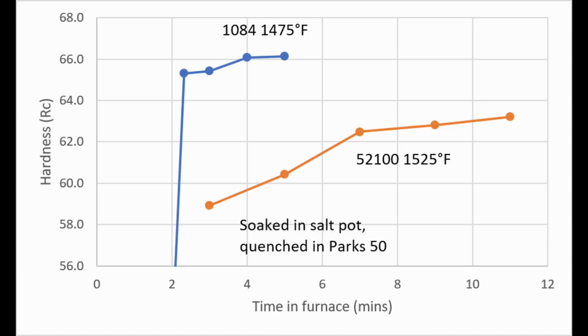So I see lots of knife makers say that they only use 5 minutes, and with a steel like 52100, that gets you in this sharp transition range, where with a thick piece of steel, you're going to be significantly softer than you are with a thin piece of steel. And so different sizes of knives or different conditions are going to result in highly variable heat treatments and highly variable properties at the end. So sometimes knife makers say that I soak way too long, like 10 to 30 minutes for different steels and austenitizing temperatures. That's not that long.